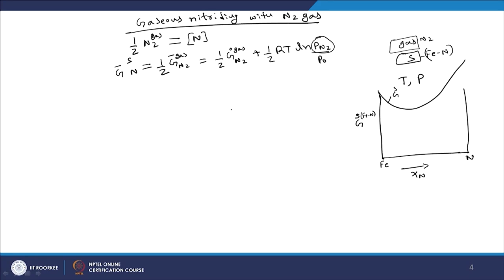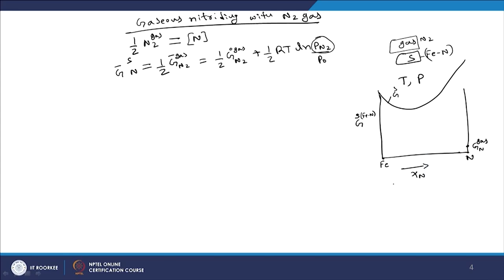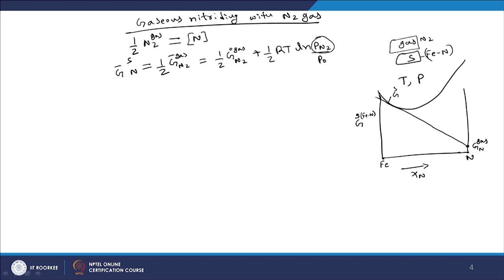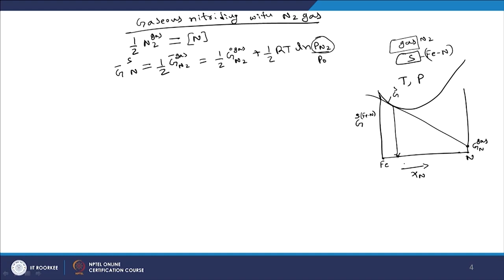N2 is a very stable molecule, so it will have a largely negative Gibbs energy. The chemical potential of nitrogen in the gas corresponds to this value on the diagram. When you draw the common tangent between the Gibbs energy curve of the solid and the Gibbs energy of the N2 gas, this tangent point gives you the equilibrium amount of nitrogen that can dissolve into solid iron for the given gas at a given temperature and pressure. To increase this equilibrium solubility, the possibility is to change the value of chemical potential of nitrogen in the outer atmosphere — for example, by increasing the pressure of N2, we can increase this chemical potential and thereby raise the equilibrium nitrogen content in the solid.